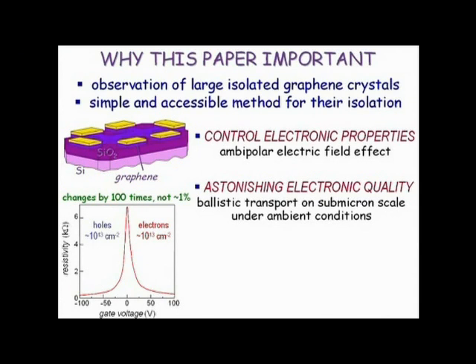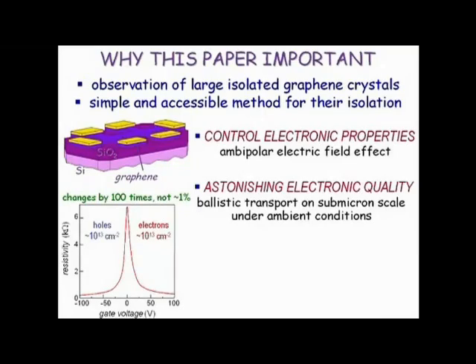The graphene is placed on a rough substrate, covered with adsorbates, all sorts of rubbish around, and still electrons move through the material like bullets without feeling what is outside. The weather outside, ambient conditions, are not important. It's completely counterintuitive. The thinner the film you usually make, the worse its properties.